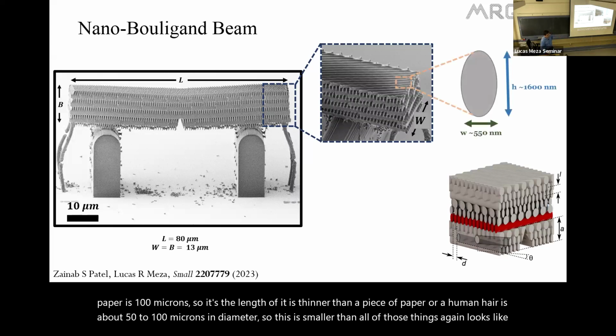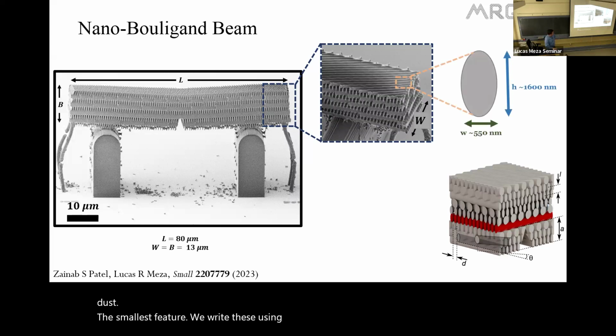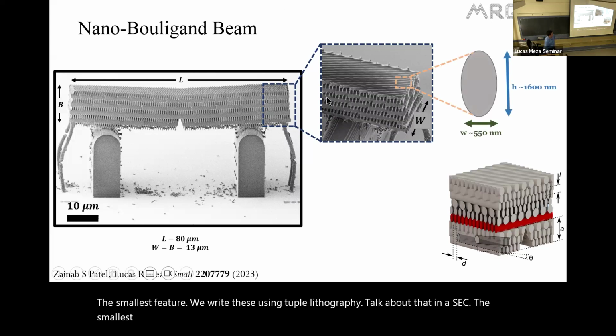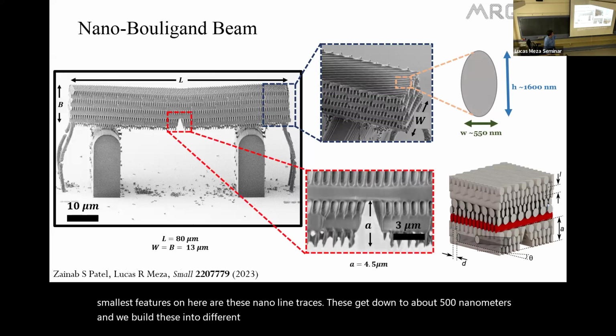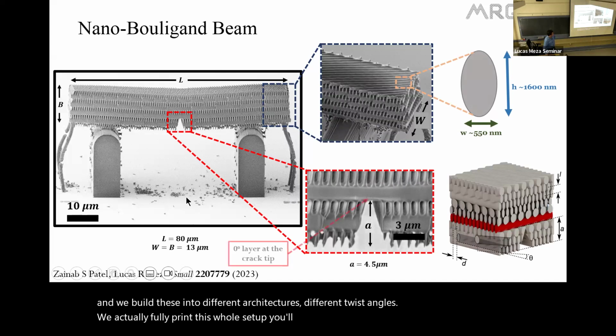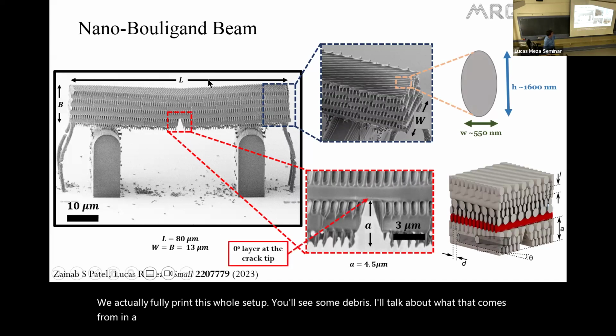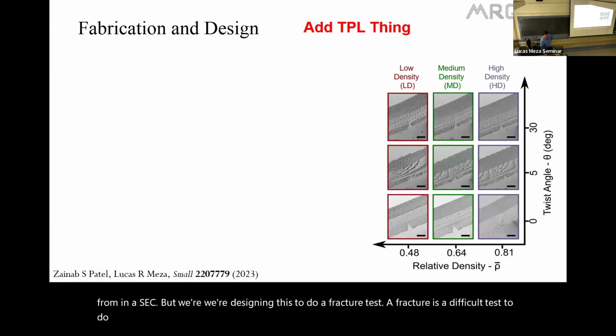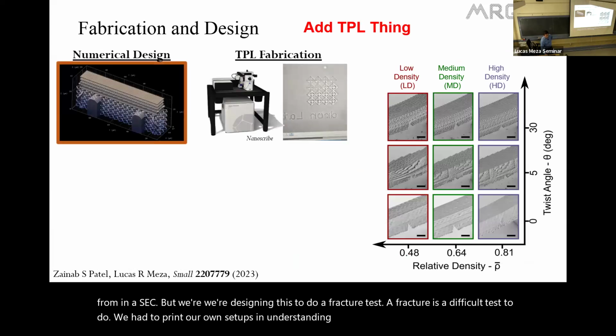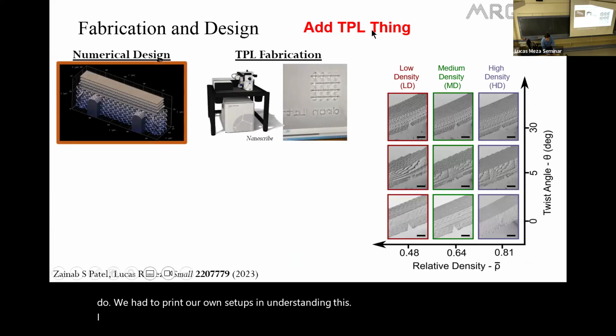The smallest feature, we write these using two-photon lithography. I'll talk about that in a sec. The smallest features on here are these nano line traces. These get down to about 500 nanometers. And we build these into different architectures, different twist angles. We actually fully print this whole setup. You'll see some debris. I'll talk about what that comes from in a sec. But we're designing this to do a fracture test. Fracture is a difficult test to do. We had to print our own setups in understanding this. Oh, I did add the TPL thing. I didn't delete that. That's fine.